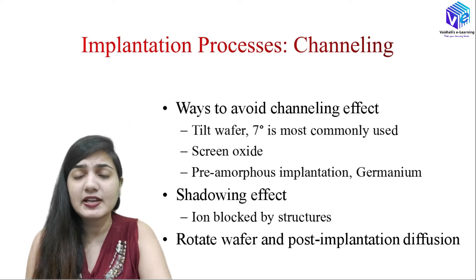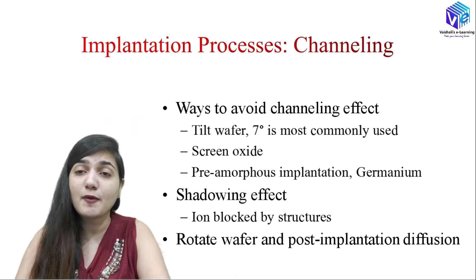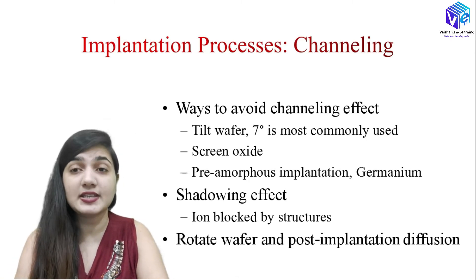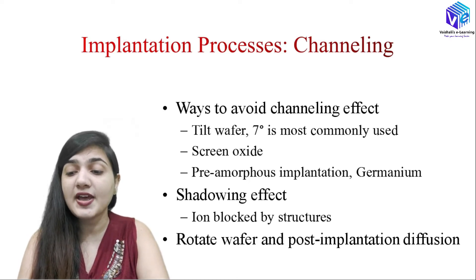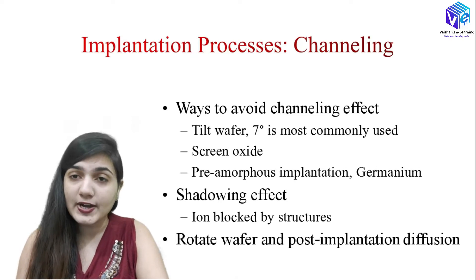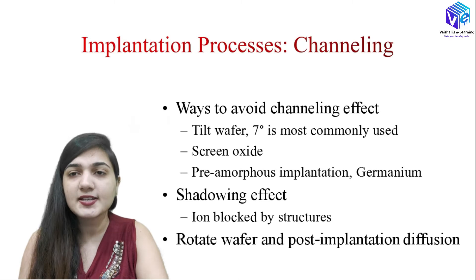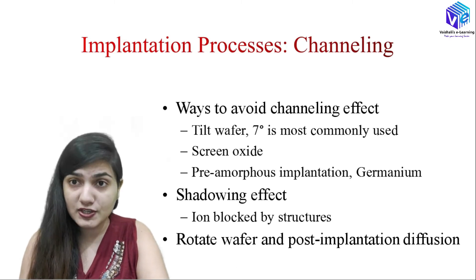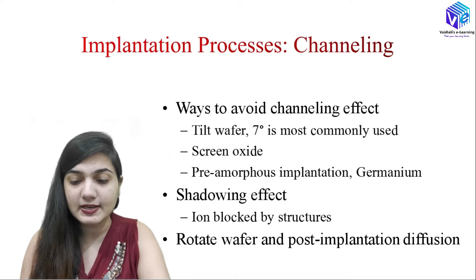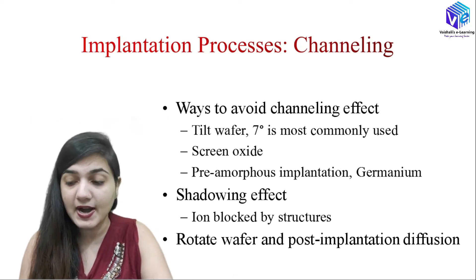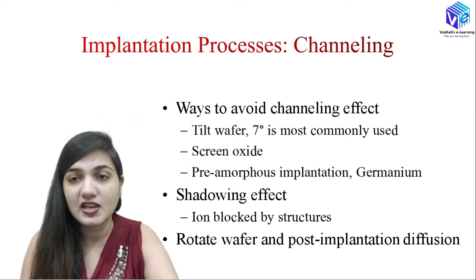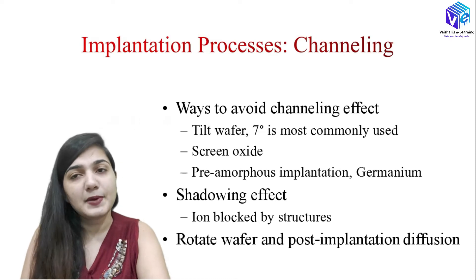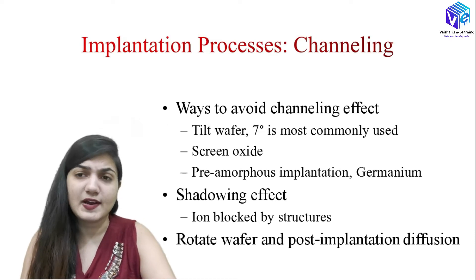Now, coming to the ways to avoid the channeling effect. I can tilt the wafer seven degrees, which is the most commonly used channeling avoidance technique. I can use screen oxides — if I use screen oxide, the amount of collision will increase and the channeling effect will decrease. I can also use pre-amorphous ion implantation, like using a germanium surface. This pre-amorphous implantation will result in much less channeling effect than normal implantation.